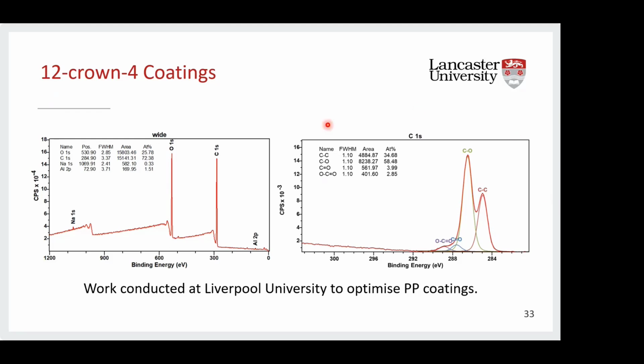And as you can see in this C1s XPS spectrum here, they have maximised this CO content, and it's obviously much higher than what we saw in the 15 crown 5 coatings. So hopefully over the next 18 months, what we expect is to see these coatings just improve further and eventually begin to approach those levels seen in the industrial standard.